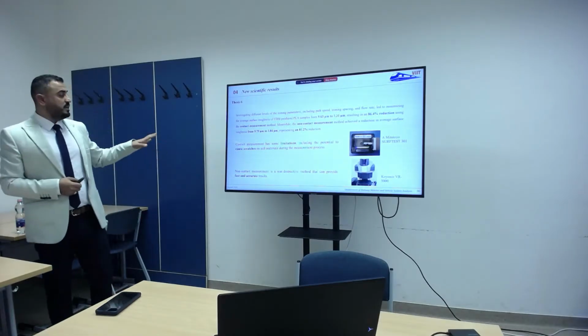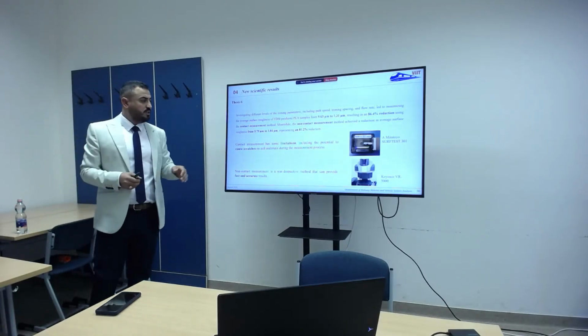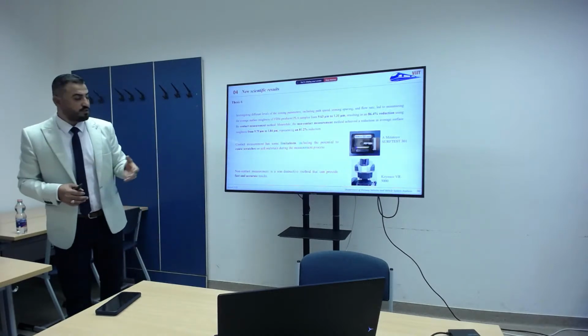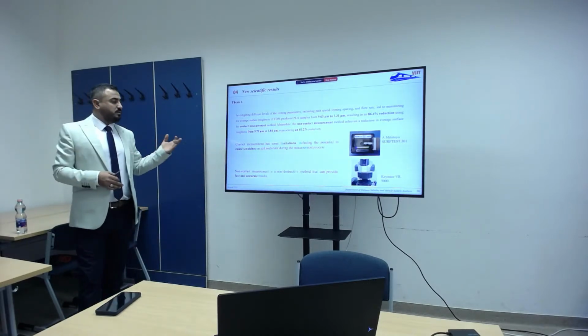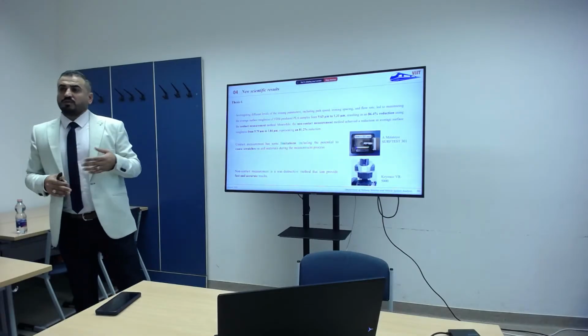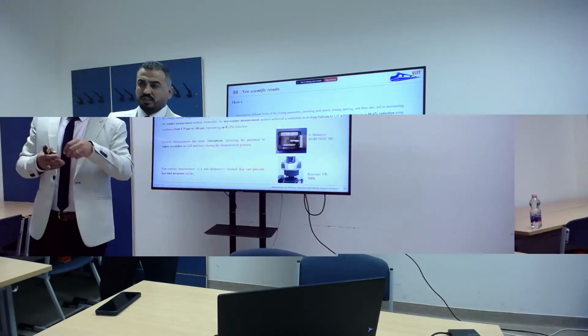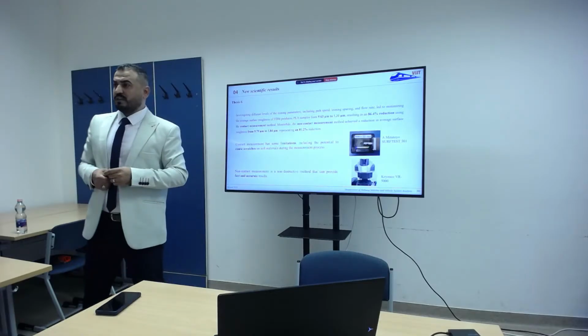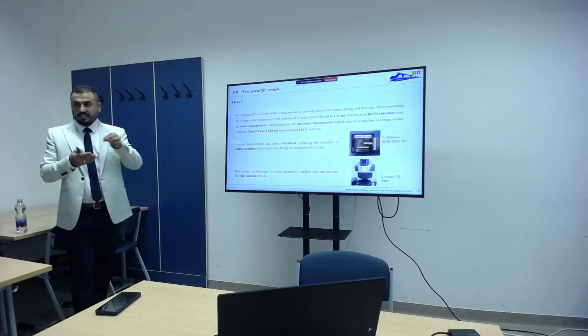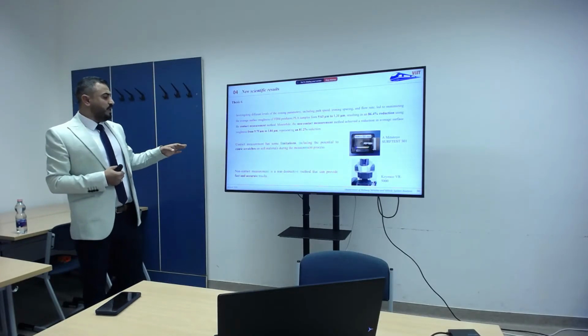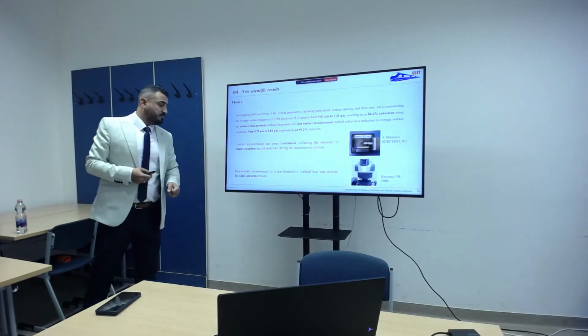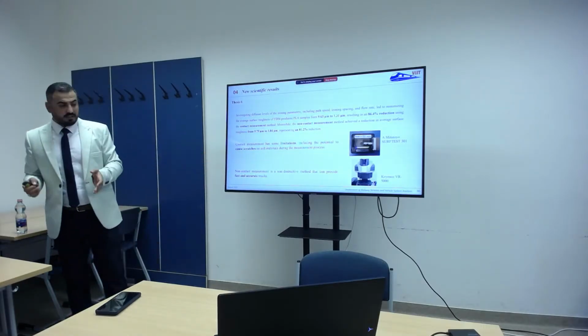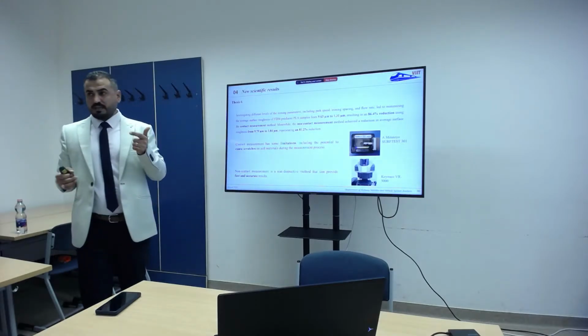Also, I found that the contact measurement has some limitations, including the potential to scratch soft materials. It also has limitations in investigating low values of surface roughness because of the tip of the stylus. The non-contact method is a non-destructive method and can give fast and accurate results.